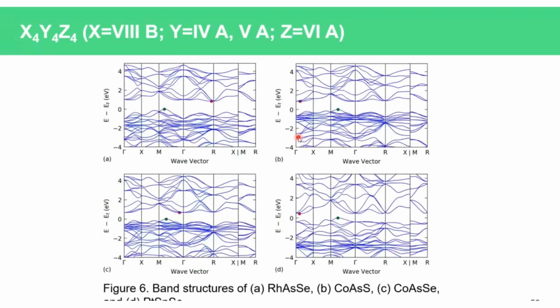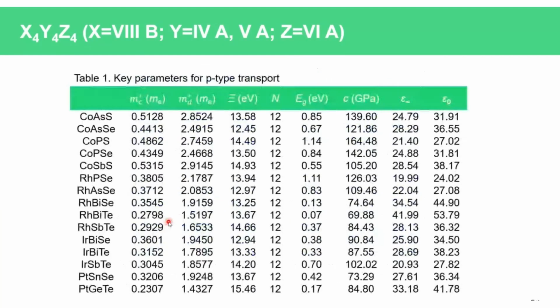This page shows their band structure. I use these 4 compounds as an example. Their CBM can locate along several different paths, but their VBM is just along the gamma-M path. The band degeneracy of the point along the gamma-M path is large, n equals 12, which means there are 12 symmetry equivalent carrier pockets in the Brillouin zone, which will result in a very high density of state effective mass. Meanwhile, the VBM are dispersive and should have small conductivity effective mass. According to our calculation, they truly have small MC and large MD.